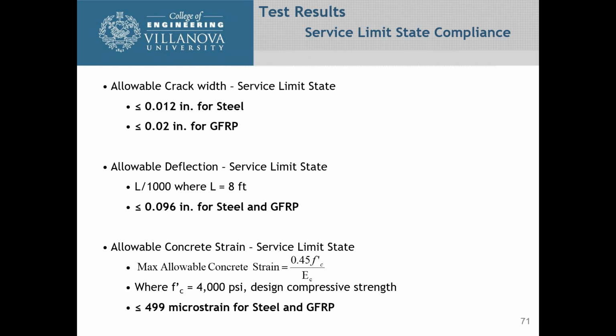Looking at AASHTO requirements for deflection, we're going to base this on L over 1,000, where L is equal to 8 feet. And that's the same whether it's GFRP or steel, and that's 0.096 inches. And the last thing we're looking at is the allowable concrete strain at the service limit state. So the maximum allowable concrete strain is equal to 0.45 f'c divided by the modulus of elasticity of concrete. And we're using the 4,000 for the design compressive strength because that's what we're designing for. Based on that, it has to be less than or equal to 499 microstrain for steel and GFRP.